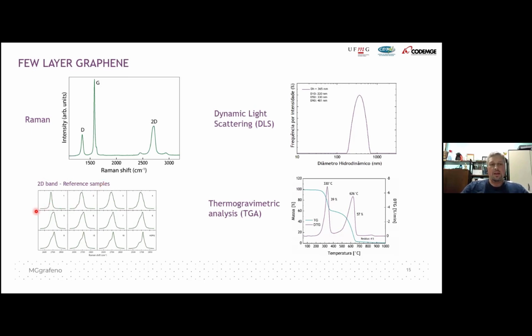For 1 layer, it looks like a single Lorentzian peak, and for 2 layers, it changes, and 3, 4, 5, 6, 7. It changes a lot if you change the number of layers. And this is because the electronic structure changes with the number of layers at this scale, okay? And this is very useful.